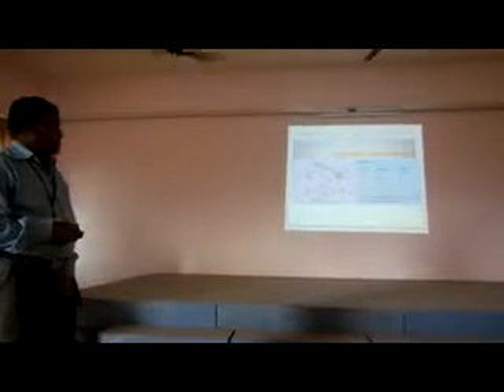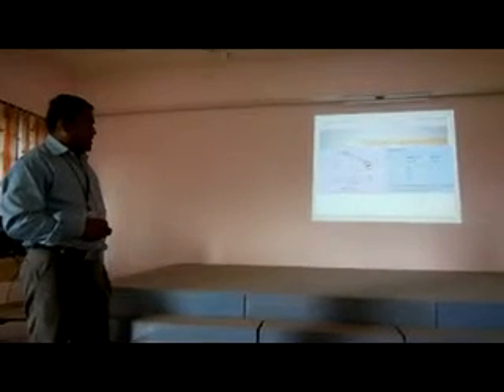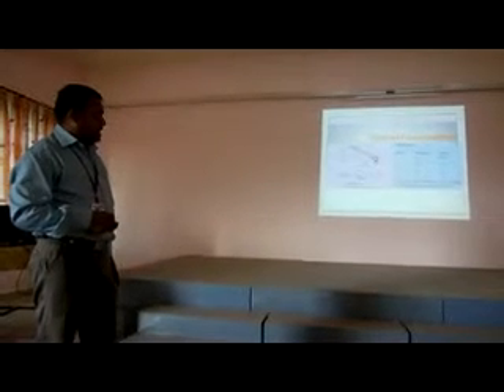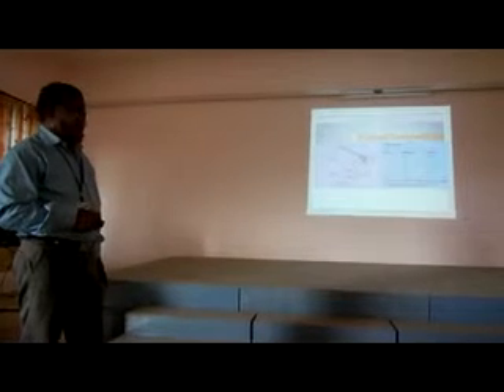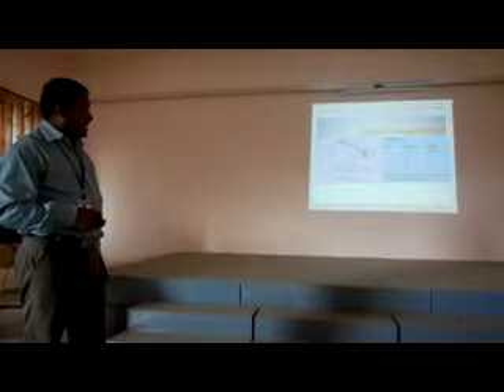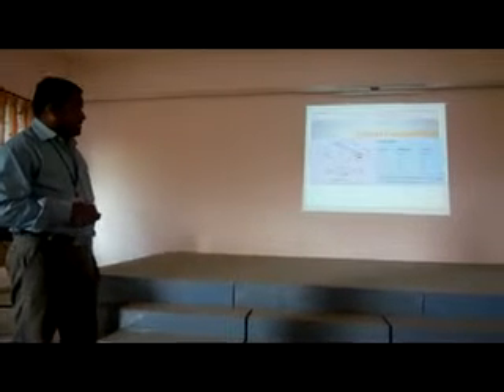And the table shows the chemical composition of the base material, and the figure shows the testing arrangement, that is the weld metal arrangement. The 300 mm plate was cut into a single bevel groove, and it was welded with the GMAW process with three different heat input conditions. The filler wire is austenitic stainless steel filler, the welding current of 250 amps and arc voltage of 28 volt was maintained, and it was welded with a preheat temperature of 150 to 170 degrees Celsius. Here the varying parameter is the welding speed. Within that, the heat input is achieved between 0.6 kJ per mm, 1.2 kJ per mm and 1.8 kJ per mm.